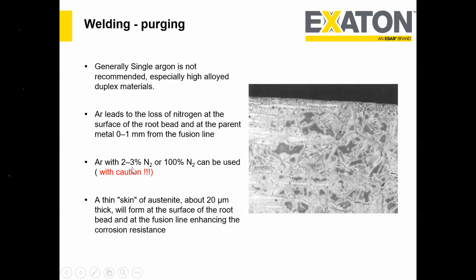So argon with 2 to 3% nitrogen or 100% nitrogen can be used. I put it with caution, as I told you that nitrogen has a good potential for the corrosion property, but make sure that we do not have the risk of having even less than 30% ferrite. We can get like 25% ferrite, which is also not good. Yeah, so this is what I explained, that a thin skin of austenite, about 20 micron thin, forms on the surface of the root bead fusion line, enhancing the corrosion resistance.